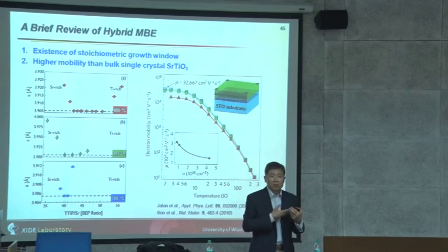But solid state epitaxy makes it much harder to get high quality material, because any non-stoichiometric element comes to the surface and leaves a lot of junky layer. Also, very limited substrates can grow epitaxial thin films. For example, when the first high TC thin film was made, people tried to grow yttrium barium copper oxide on MgO, magnesium oxide, and yttria stabilized zirconia. They used all kinds of substrates, and everything turned out to be insulator.